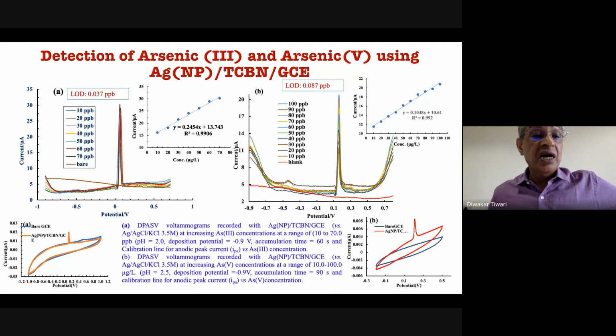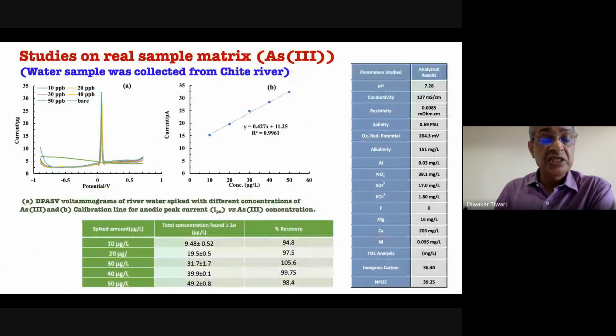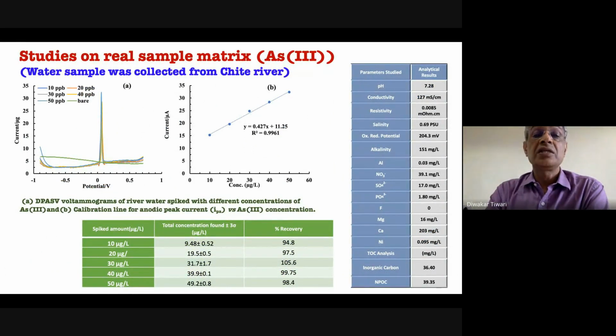So with that, the LOD of this detection of arsenic 3 and arsenic 5 was obtained, and it is 0.037 ppb and 0.087 ppb of the arsenic 5 that we could achieve with the help of these materials, these fabricated electrodes. The question was, can we use it for the real water? So real water that we have collected, the Chite river water, and with that we tried, here again we could get a very good straight line, the calibration line.